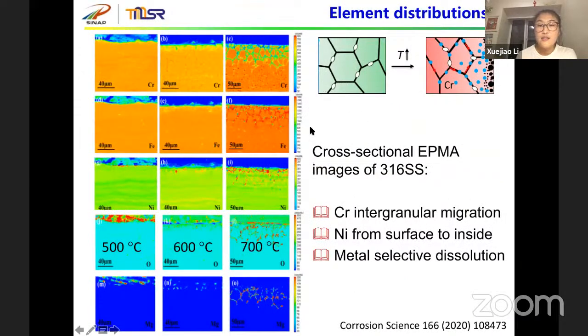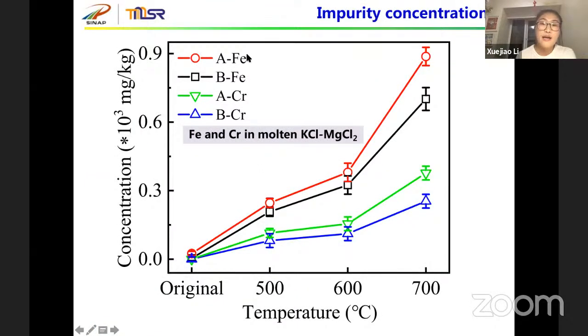From the element distribution by EPMA, we can clearly see the distribution of metal and non-metal elements, and further analyze the corrosion mechanism. For example, the intergranular migration of chromium can be found as temperature increases, and the nickel transports from the surface to the inside of the alloy. Besides, the selective dissolution of iron and chromium from the alloy into the molten salt can be verified by the increased ionic concentration.